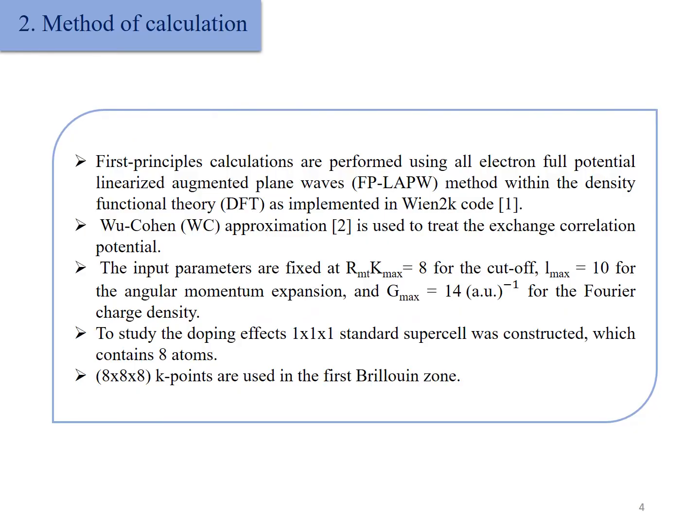To do so, we used first principles, all-electron full-potential linearized augmented plane wave FP-LAPW method within the density functional theory as implemented in the WIEN2k code. WC approximation is used to treat the exchange correlation potential.